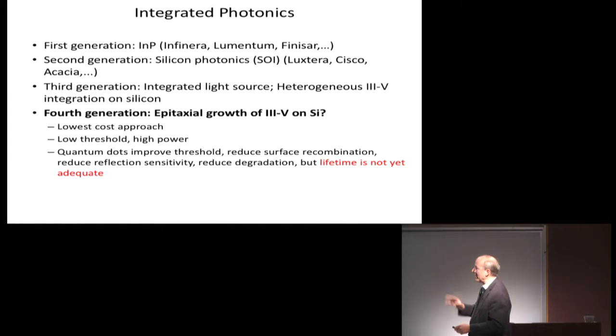And I'd suggest perhaps there's a 4th generation. And in this case, not just Eli, but Intel and others wouldn't agree with this, although we actually work closely with Intel on this: epitaxial growth of III-V on silicon. The main reason for that now is we get away from bonding individual chiplets. We get away from having to do epitaxial growth on expensive substrates. So it is the lowest cost approach. We don't have the advantage now of being able to bond different chiplets adjacent to each other. We've got to do regrowths like Infinera does today. So you save a lot on wafer cost.